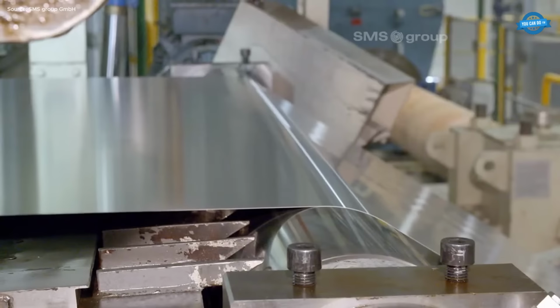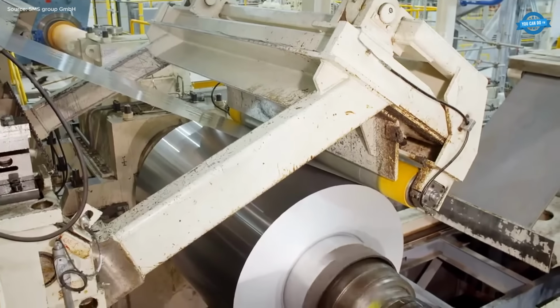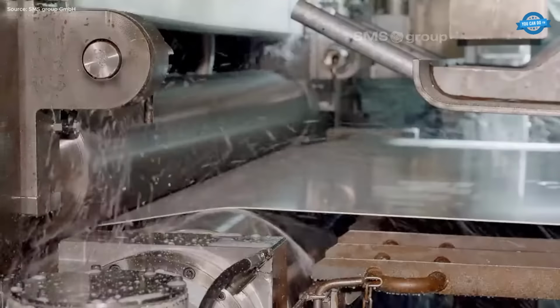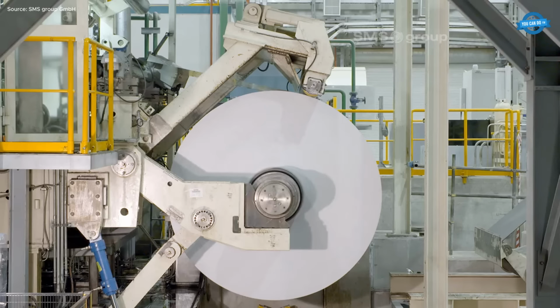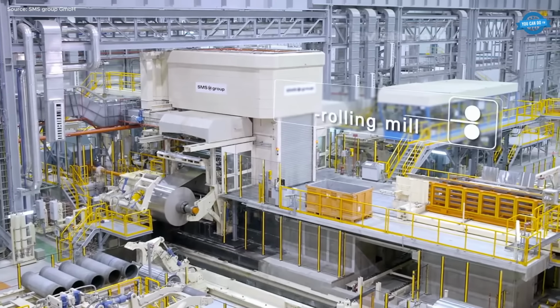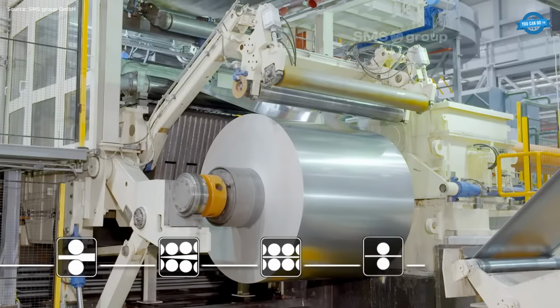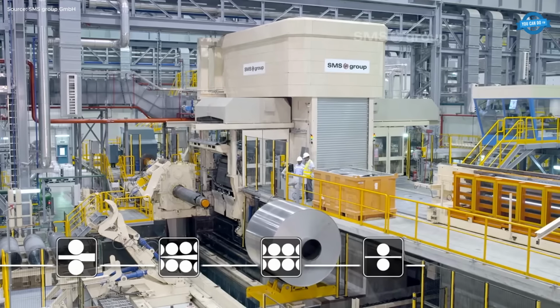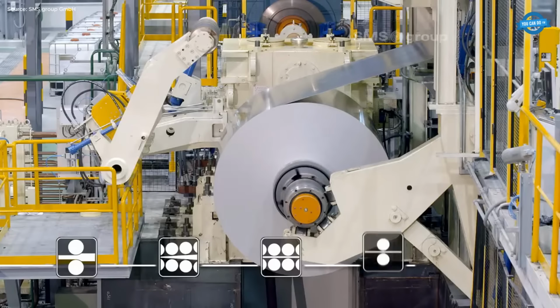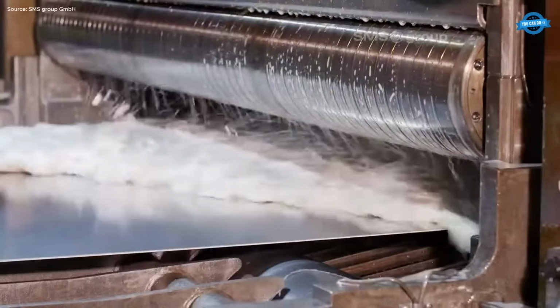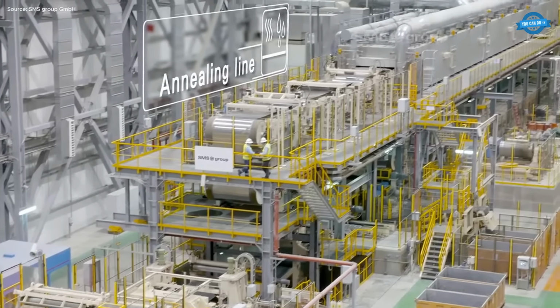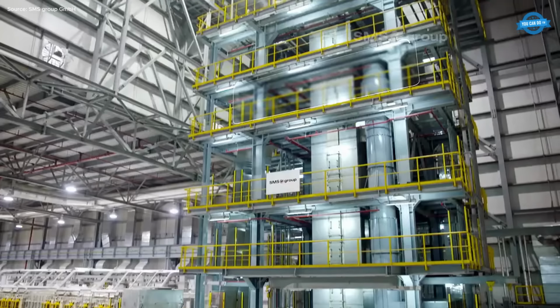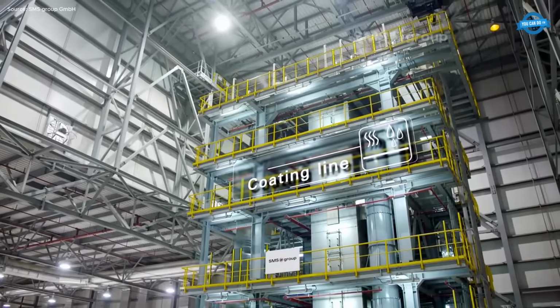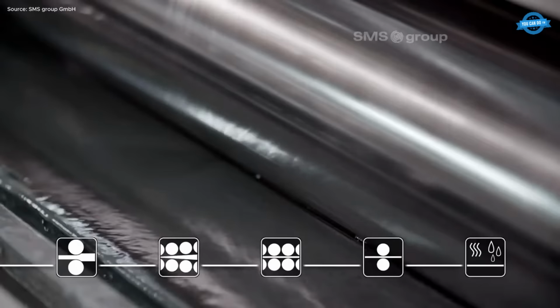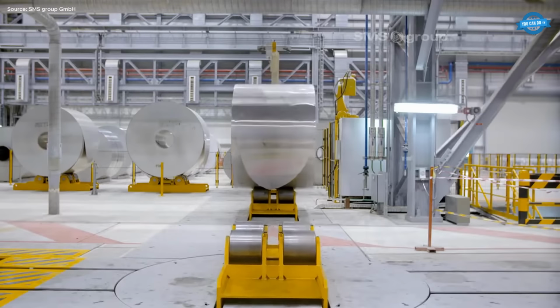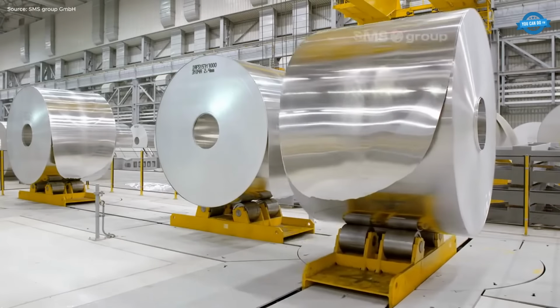A tandem cold mill and single-stand cold mill reduce material further to 0.15 mm with laser-based flatness control, AGC, automatic gauge control, and rapid roll change systems. For automotive grades, a heat treatment and chemical coating line applies precise annealing, cooling, and corrosion-resistant coatings. Full X-Pact automation, real-time monitoring, and plug-and-work simulation ensure seamless control and reduced commissioning time. This setup guarantees consistent strip quality, high throughput, and process efficiency.